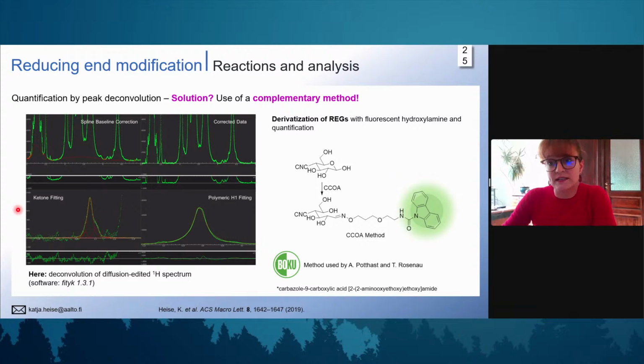It's a fluorescent hydroxylamine that is attached to non-modified reducing end groups, like on the pristine cellulose nanocrystals. And you can then quantify this derivative by fluorescence spectroscopy. You can also couple this with GPC measurements. And it's a method that has been developed by Andreas Potthast and Thomas Rosenau at BOKU in Vienna. And this works really nicely. So we always use, together with our NMR spectroscopy, complementary methods for a proper analysis.